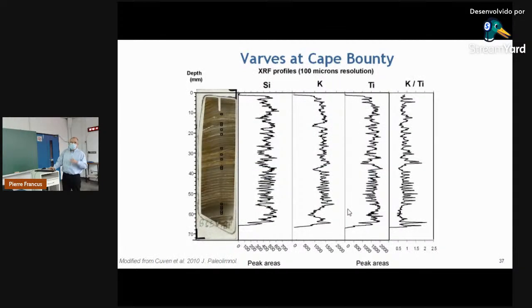Let's go for the clay cap. If we look at the maximum of potassium, and here we have made the ratio of potassium to titanium to really pinpoint and recognize the clay caps, and this is really doable. And these peaks here are really useful to recognize and count the clay caps. So with that, we can have our Varve counting and the chronology established with the help of this. Of course, we will also use the peak counter software that I showed earlier.